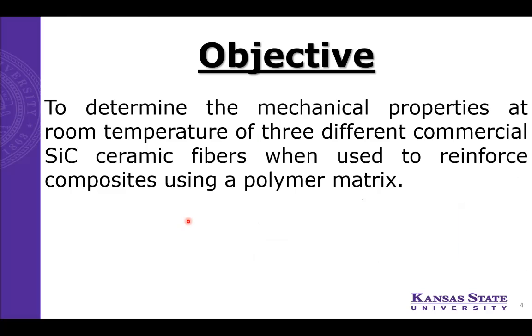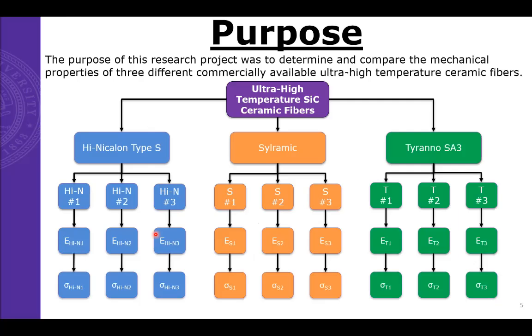So our project was to determine the mechanical properties at room temperature of 3 different commercial silicon carbide ceramic fibers when used to reinforce composites using a polymer matrix. So we accomplished this by comparing the Hi-Nicalon type S, Sylramic, and Tyranno SA3 fibers. We made 3 composites of each of these fibers, using each of these fibers as reinforcement before tensile testing them to get the elastic moduli and the tensile strengths.